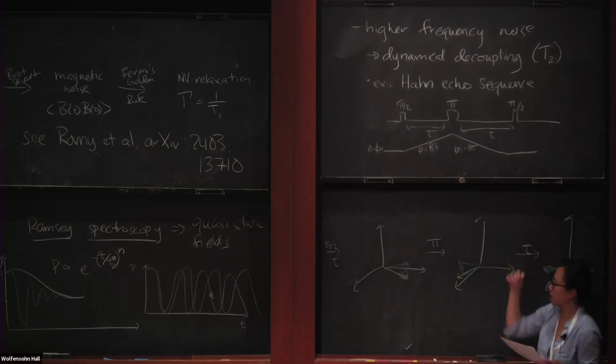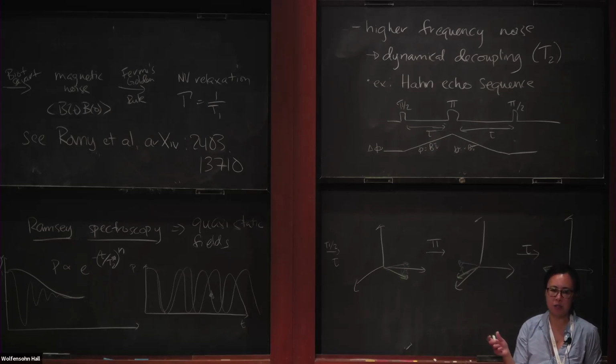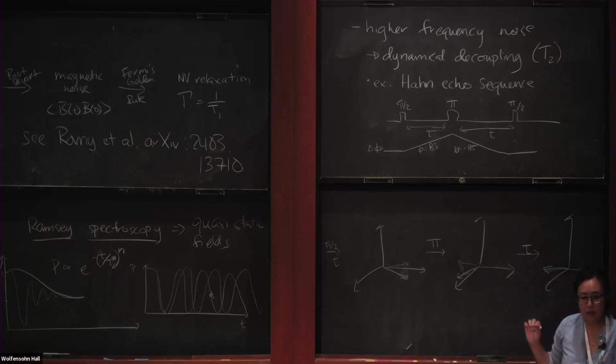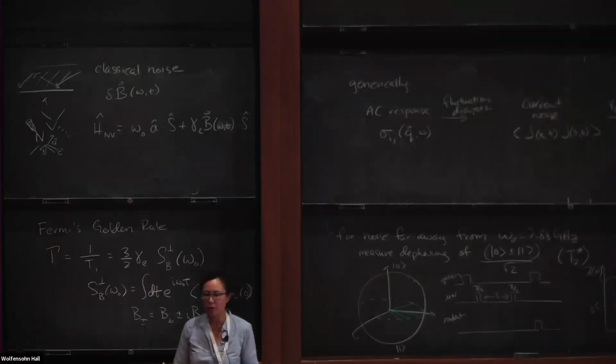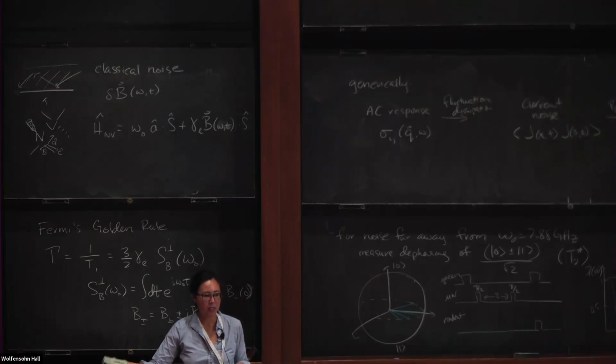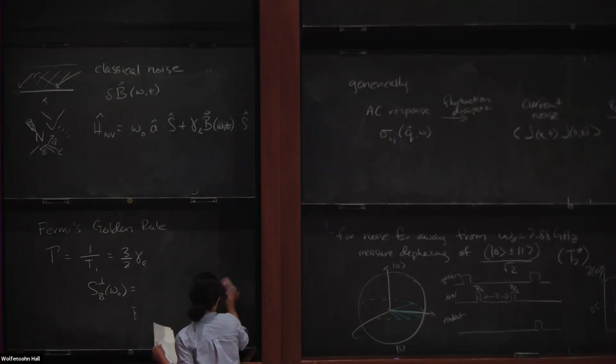Okay, so the key is this allows you to cancel, in NMR, what people use this for is to cancel out static inhomogeneity in your magnetic field, because you're not that good at making a magnet that is perfectly homogeneous over your whole sample volume. And one way to cancel out all of that inhomogeneity is just by doing a Hahn echo sequence. In our case, what we care about are quasi-static fluctuations in the magnetic field, which can arise from, for example, slowly fluctuating carbon-13 nuclei in the environment, right? So you have these very long T1 nuclear spin flips that set your bare T2 star.